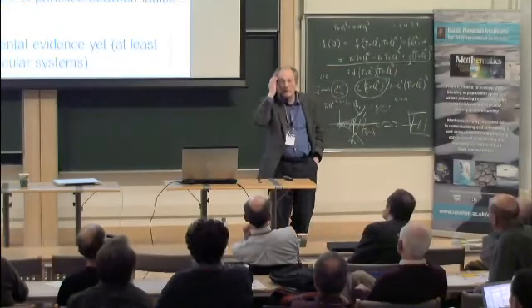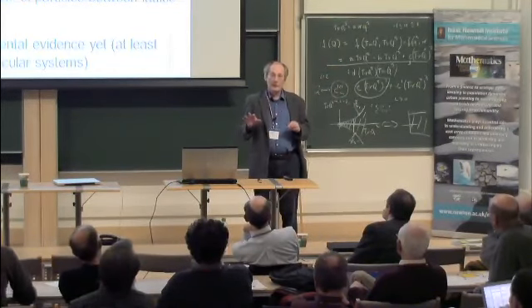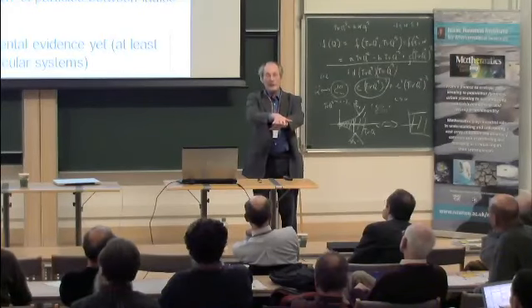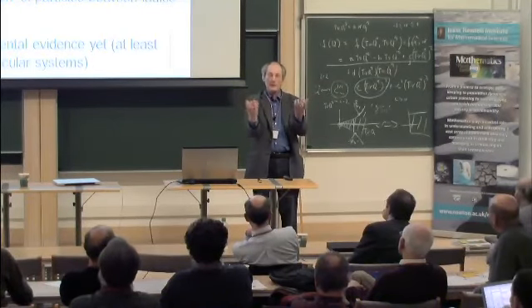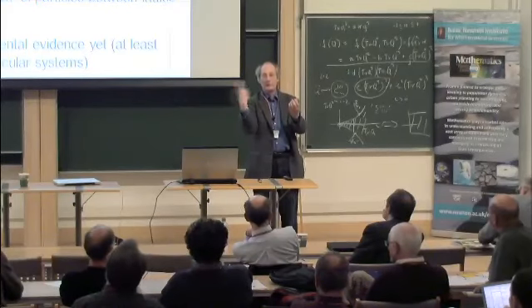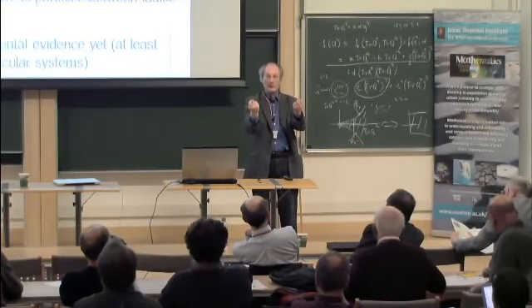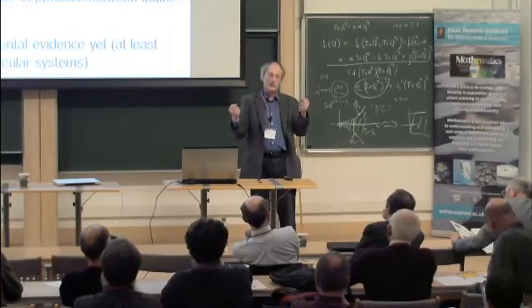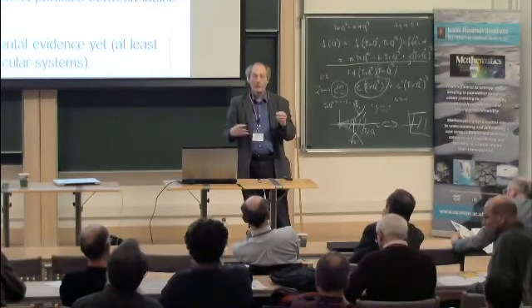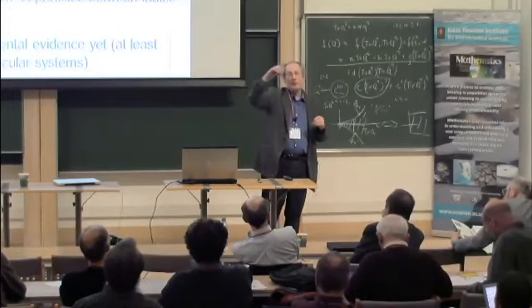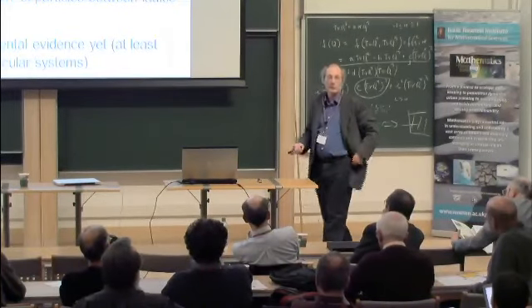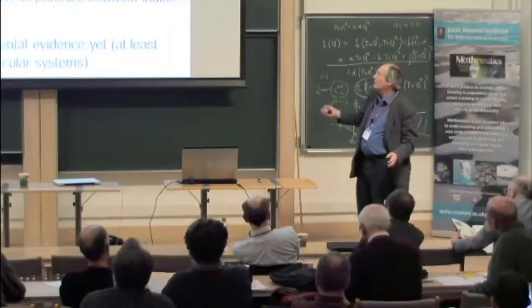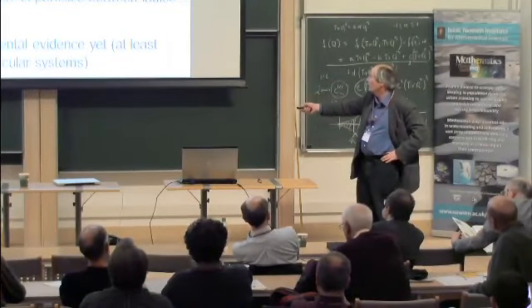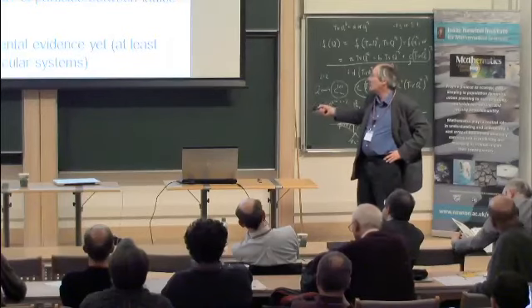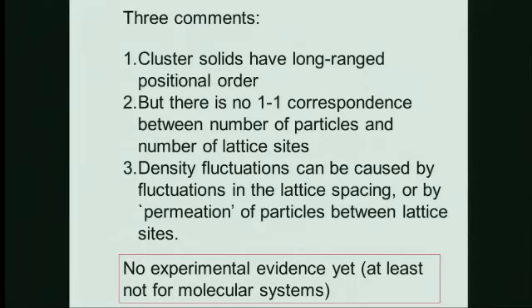Again, there's a special case. If you take a two-dimensional electronic system, so a two-dimensional electron gas in a very strong magnetic field, at a quantum Hall step, you get electron bubbles, and they're basically electrons in their Landau level. The interaction between electrons in their Landau level is very much like this truncated Gaussian, and so they can have 1 or 2 or 3. Unfortunately, you can't follow the whole phase diagram, because by the time you get to the critical point, I think they go into different phases. But for molecular systems, there are predictions that dendrimers should do it. I'm not aware of any convincing experimental demonstration yet.